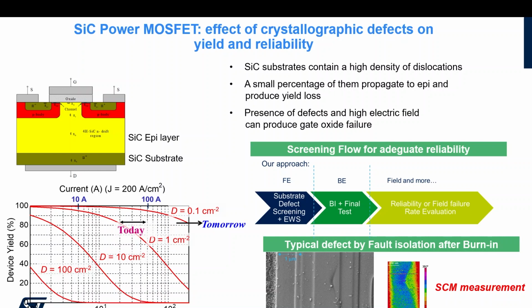So as you can imagine, the material study on the substrate and the epitaxy is continuously improving the properties. Today we are well below 1 defect per centimeter square on the surface, and we are progressively going to 0.1 per centimeter square. In some cases, some killer defects have been completely eliminated. Having said that, you cannot stop because the application is there.